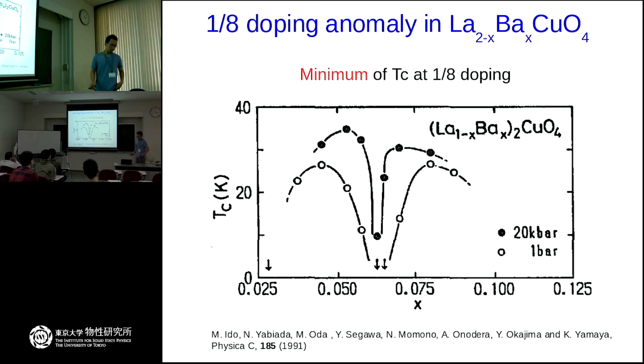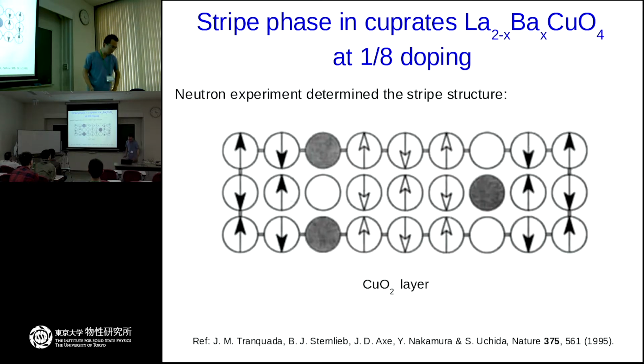So let me go to the experiment. Shortly after the discovery of the first cuprate superconductor, people found that in this material at 1/8 doping, if we look at the transition temperature, there is a minimum here. Later on, people used other experimental techniques to determine the stripe structure at 1/8 doping. The stripe structure is like this. The holes are concentrated on lines, and between two stripes, the electrons are antiferromagnetic.